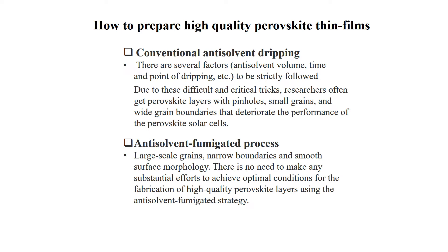However, there are several factors we need to keep in mind, like the volume, the timing, and at which point to drip this solvent. These must be followed very strictly; otherwise you will get thin films with many cracks, pin holes, small grains, and grain boundaries, which can affect the performance of your device.